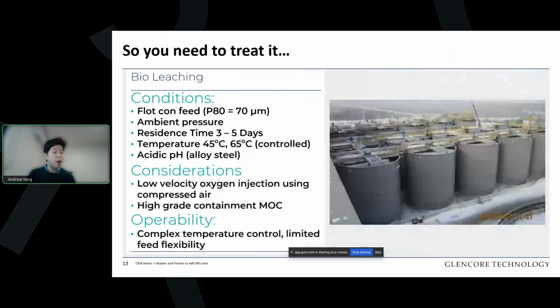Another option is bioleaching, which uses bacteria. Bioleaching reactors are operated at low temperatures, but because they're using bacteria, the residence time is much longer for the process. We're talking multiple days, almost a week and sometimes more. And because we need to keep the bacteria alive and thriving, the temperature range is much lower and much tighter. So we're talking between 45 to 65 degrees there. Once again, because we're dealing with live bacteria, the process can be quite finicky and needs to be quite precise, and complex temperature control is required.